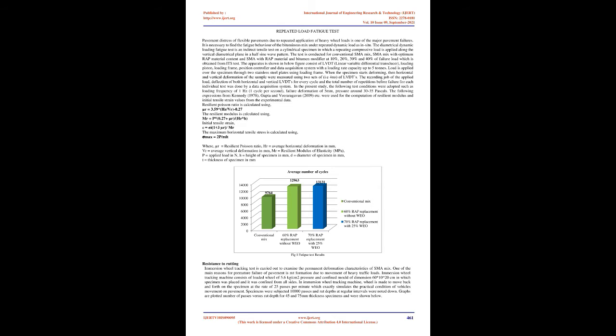Waste engine oil, WEO. Reclaimed asphalt pavement, RAP, consists of aggregates coated with bitumen. The coated binder is aged and its properties are not as good as the original binder. The aged binder present in RAP lacks oily compounds and doesn't behave like fresh bitumen. In the present study, waste engine oil is used as a rejuvenator, and it was procured from a motorcycle garage in Bengaluru.